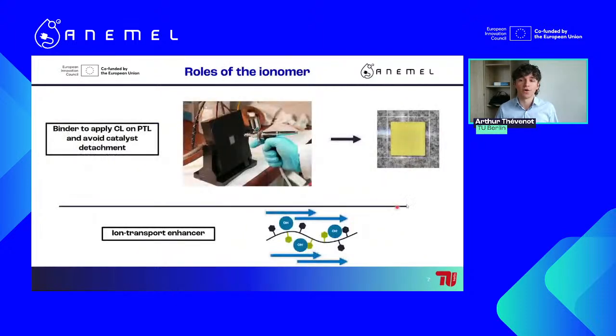What are the roles now of this ionomer? What can we do with it? Why do we need it? Well, traditionally, the ionomer was used as a binder to apply your catalyst layer on the PTL and avoid catalyst detachment. This is especially the case for powder catalysts, such as the one that we use at the anode, the nickel-iron layered double hydroxide, also known as nickel-iron LDH. So how does it work exactly? How do we prepare this?